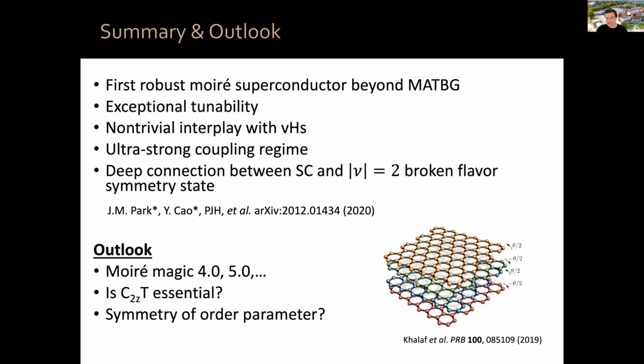This paper and the subsequent papers argue that the key to superconductivity is the symmetry, C2zT symmetry, 180-degree rotation around an axis out of plane and time reversal symmetry. It turns out magic angle twisted bilayer graphene and this mirror-symmetric trilayer graphene have this symmetry, whereas all of the other systems that I told you the superconductivity was fragile, none of those has this symmetry. We still have to check if this is true, okay? So far, the two cases we have checked, that's okay. We still have to check more. It could be that this is indeed an important ingredient.